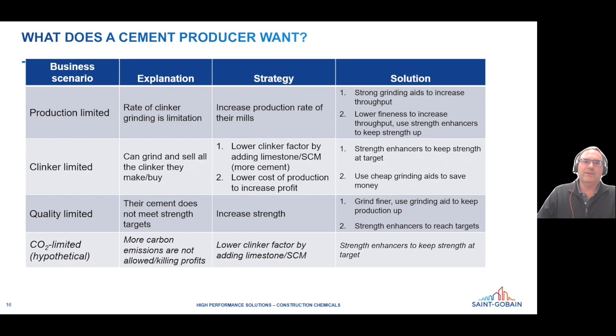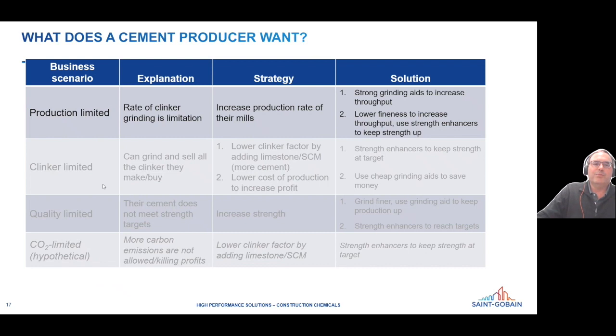So if the business scenario, as I call it, is production limited, what that means is that the manufacturer is making a lot of clinker, but he's having a hard time grinding it all. So maybe his mill capacity isn't as large as his kiln capacity. So in this case, the key strategy, obviously, is that you need to increase the rate of production. You need to increase the grinding rate. So I think the most obvious solution is you just use a really strong grinding aid that makes the process more efficient, and that certainly works.